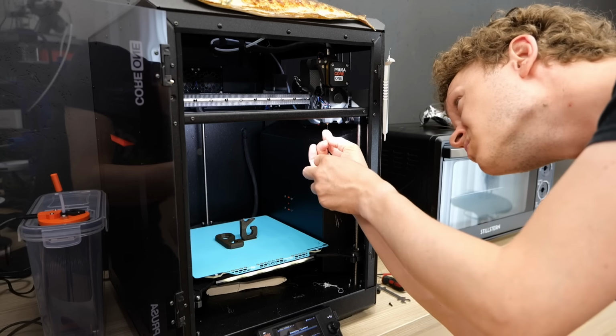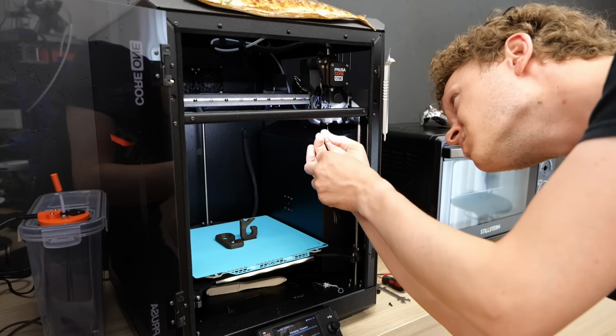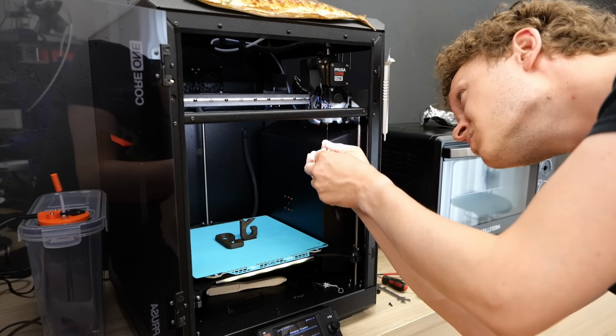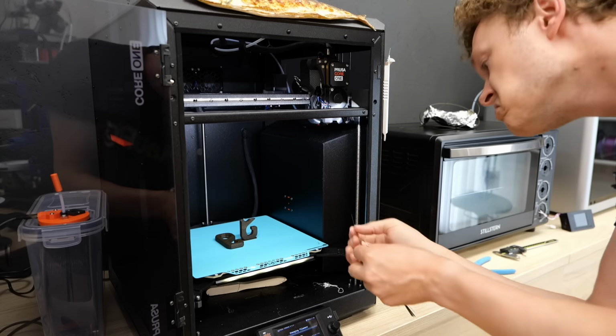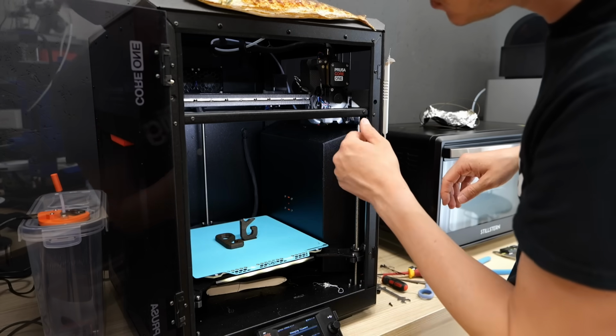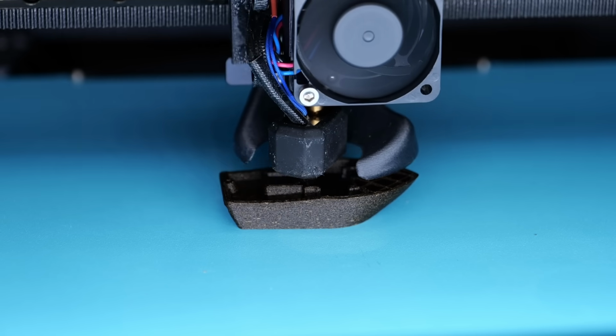I'm pretty sure that the nozzle didn't clog, but I rather had some heat creep jam, because I printed the parts during a big heat wave here and had almost 30 degrees Celsius in the studio, and also all the benchies before did print great.